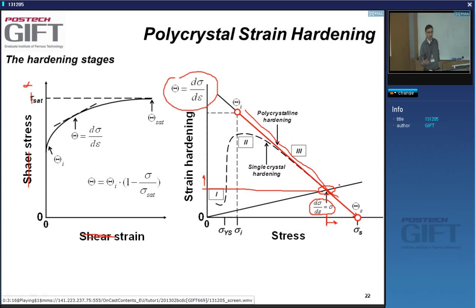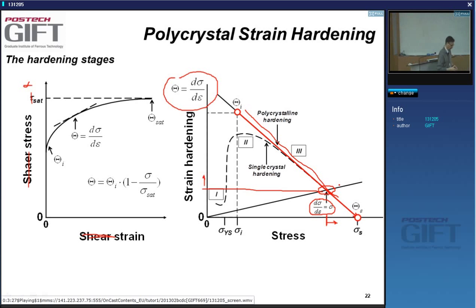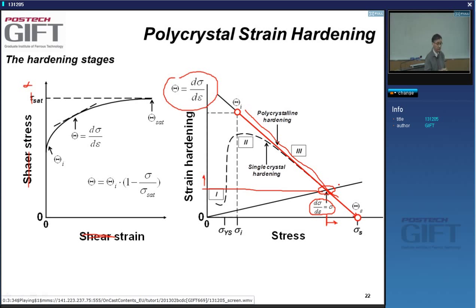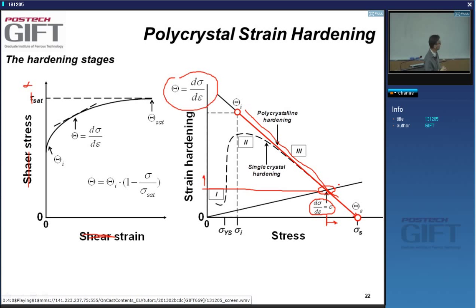You cannot really do this by adding solutes. You cannot do it by reducing the grain size. If you add precipitates, same thing. When you reduce the grain size, you actually get collapse of plasticity — you get lots of strength but no plasticity. The same holds for precipitates. If you have lots of precipitates in a solid, you will tend to see a reduction in formability.